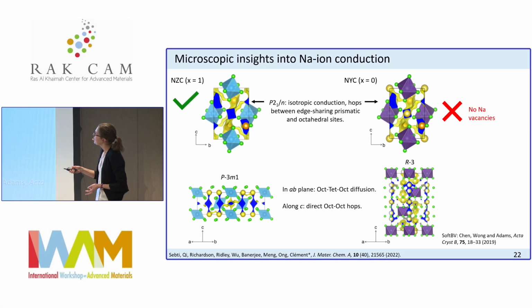So what we find for NZC, this is the much more conductive polymorph, the P21 over N polymorph. Unfortunately, this is the one where you need high energy conditions to form. So it's only with ball milling that you can form this material. So what that suggests is that if you wanted to make a much better conductor out of this material, you'd have to ball mill much more aggressively.